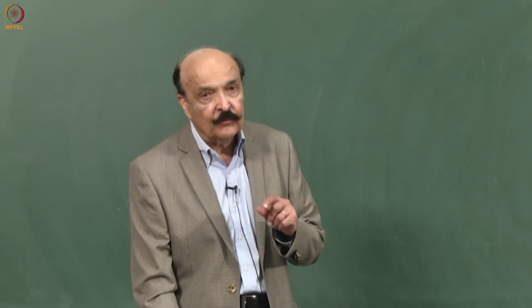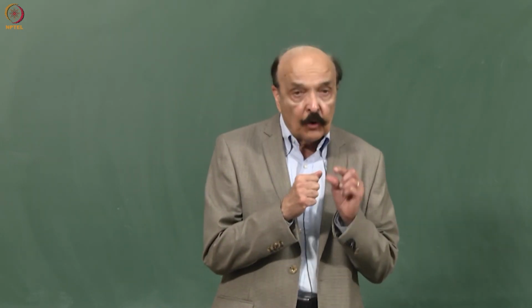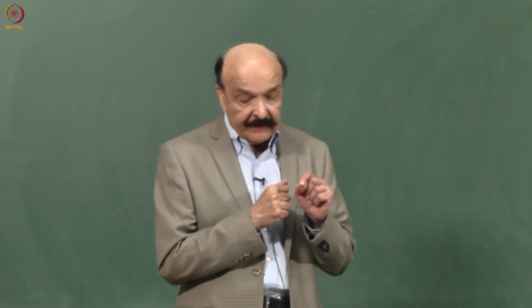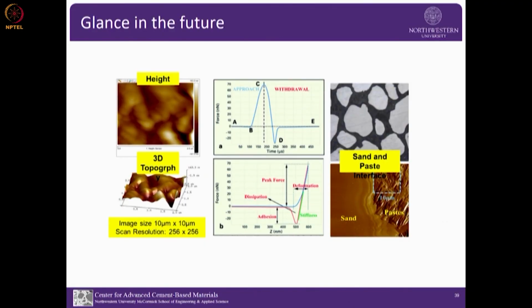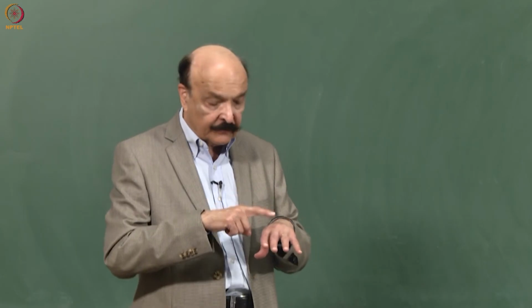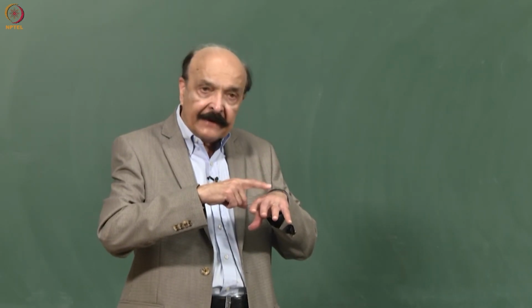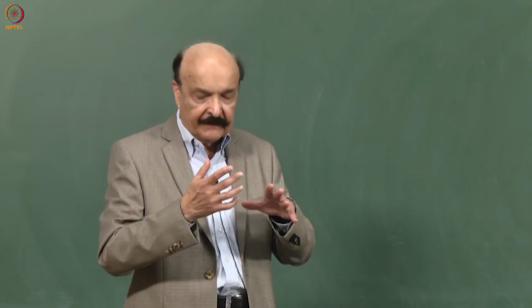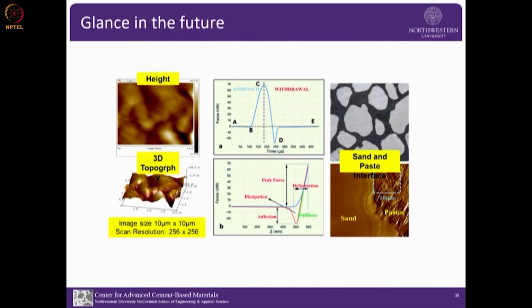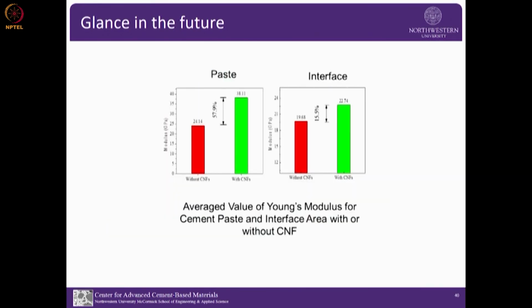To see what is happening with the aggregate, we decided to measure the modulus at the nanoscale of the interface. Now you know the interface is 10 to 15 micron, so you cannot use conventional nano indentation because the indent itself is a few micron. So we are using an atomic force microscopy needle, applied in cyclic loading. You essentially measure resonance frequency, dynamic frequency, and the force is very small, and we can measure with spacing much smaller than with conventional. Doing this, I want to show some average values. Of course, there is a histogram. This is the average increase with the addition of carbon nanofiber in cement paste and interface.